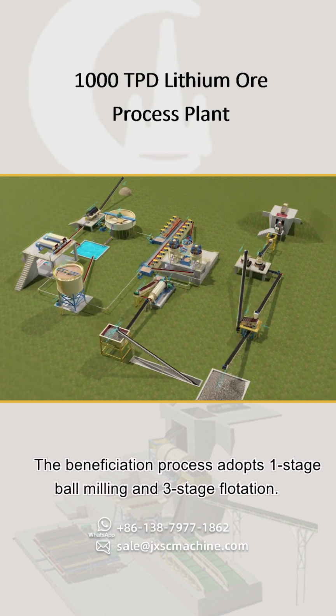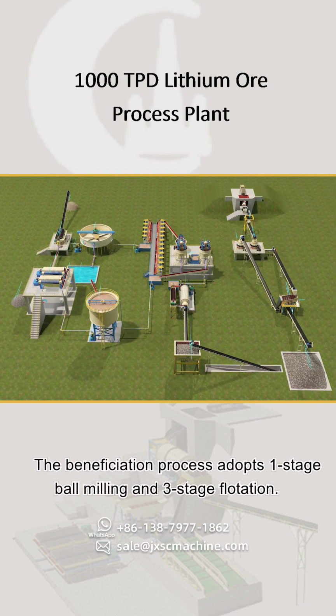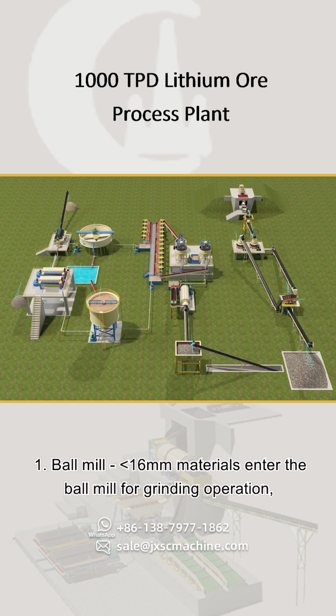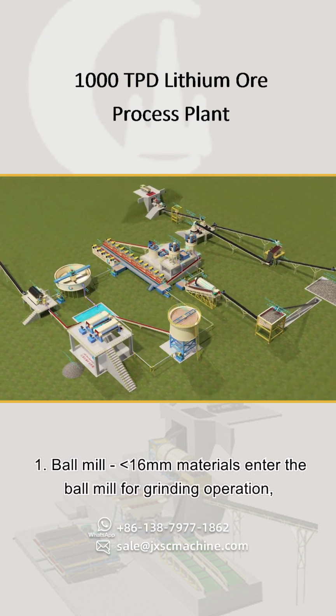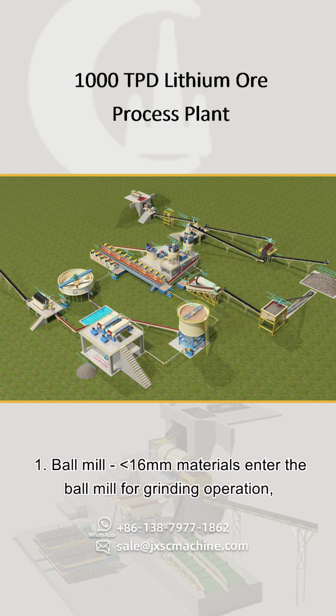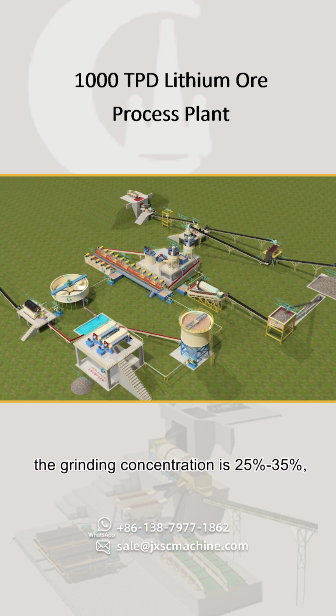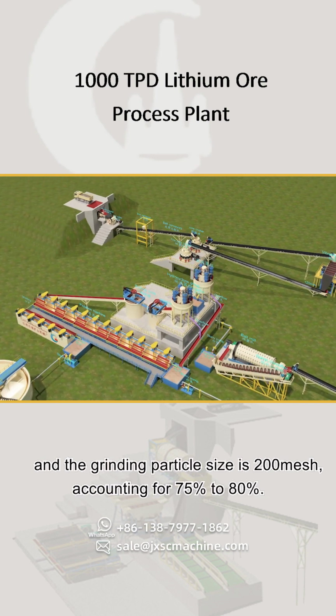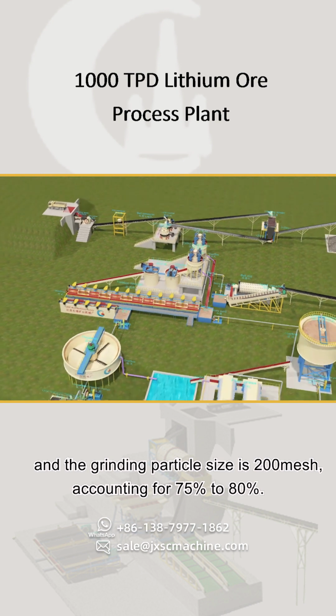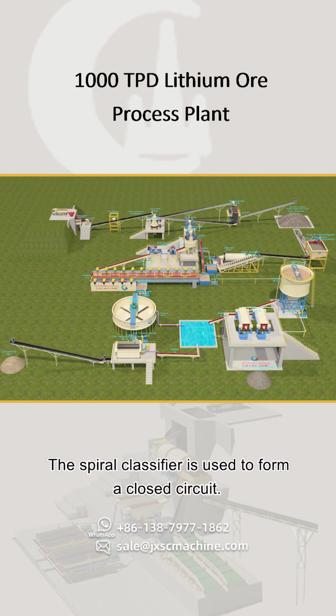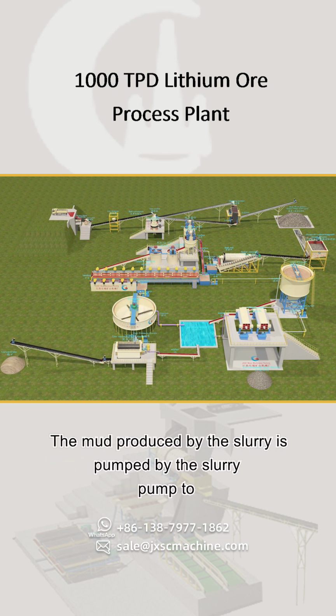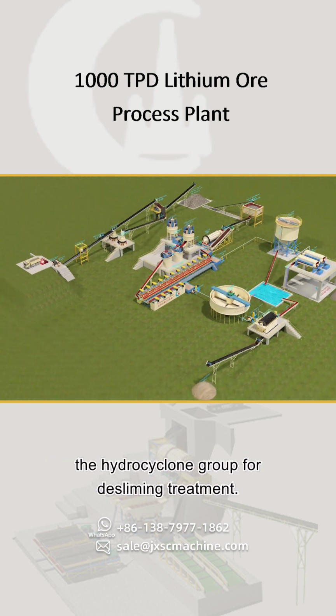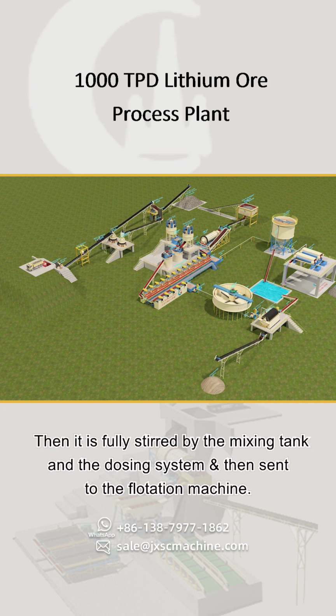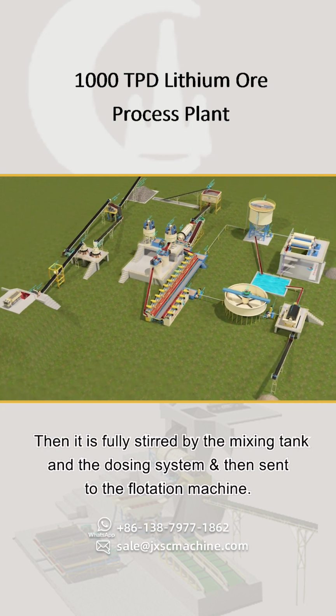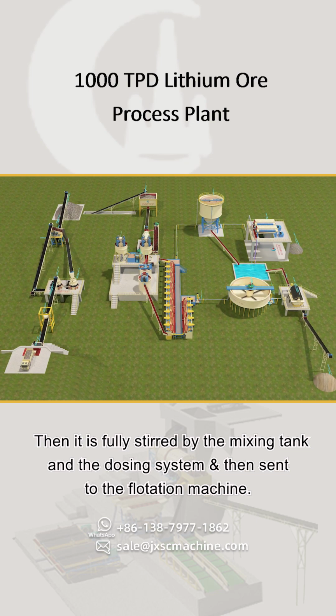The beneficiation process adopts 1-stage ball milling and 3-stage flotation. 1. Ball mill. Smaller than 16 mm materials enter the ball mill for grinding operation. The grinding concentration is 25% to 35%, and the grinding particle size is 200 mesh, accounting for 75% to 80%. The spiral classifier is used to form a closed circuit. The mud produced by the slurry is pumped by the slurry pump to the hydrocyclone group for desliming treatment. Then it is fully stirred by the mixing tank and the dosing system and then sent to the flotation machine.